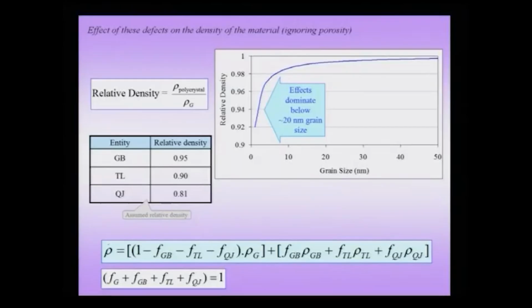Now, I can write down the density of the material using the formula that rho is equal to (1 minus fraction of grain boundary, fraction of triple line, fraction of quadruple junction) times the density of the grain. That means, if I take out all the other entities, I am left with the fraction of the grains, and that fraction I multiply by the density of the grains. Then I multiply the relative fractions of all the other entities, like the grain boundary, the triple line and the quadruple junction, with their relative densities, and I get the density of the entire composite, or the polycrystal. So, the nanocrystal, I will get the density of the nanocrystal.